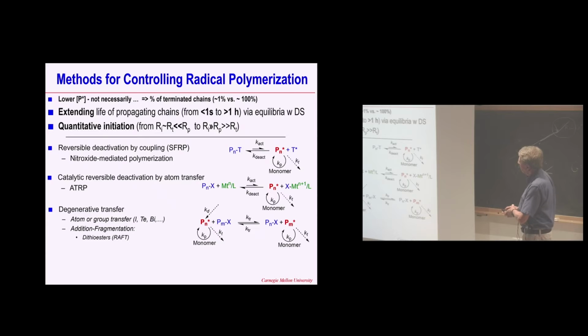This can be done by equilibrating these free radical propagating species with various types of dormant species. Dormant, which means that they are sleeping, essentially. They cannot terminate, they cannot propagate. And this bond here between the chain end and this capping agent is pretty weak. So therefore, this bond can homolytically cleave and regenerate this radical and counter-radical. This radical can propagate maybe once or twice, and then it will be converted from the active to the dormant state.